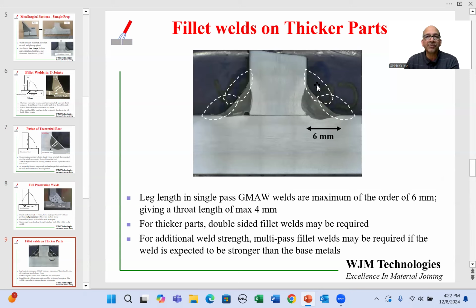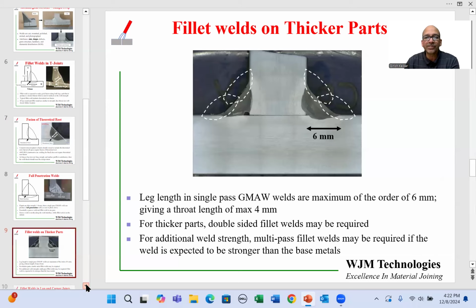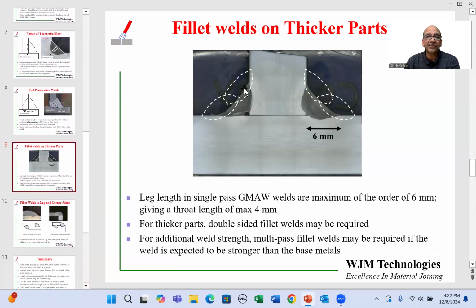So if you want a larger fillet weld, either on one side or both sides, then you have to run this in multiple passes. As I've shown over here, you'll run the first pass, and then you might add another pass, and the other one slightly higher. These additional passes are staggered so that they effectively create a triangle with a longer leg length. So that can be done too. Multipass welds or double welds produce an option. Again, of course, you have to have access to the other side, which is often not the case. So if you have access, you can have these other options for a larger weld.